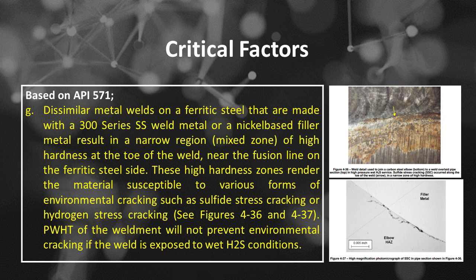conditions. See Figure 4:36, weld detail used to join a carbon steel elbow, bottom, to a weld overlaid pipe section, top, in high pressure wet H2S service. Sulfide stress cracking, or SSC, occurred along the toe of the weld, arrow, in a narrow zone of high hardness. And Figure 4:37, high magnification photomicrograph of SSC in the pipe section shown in Figure 4:36.